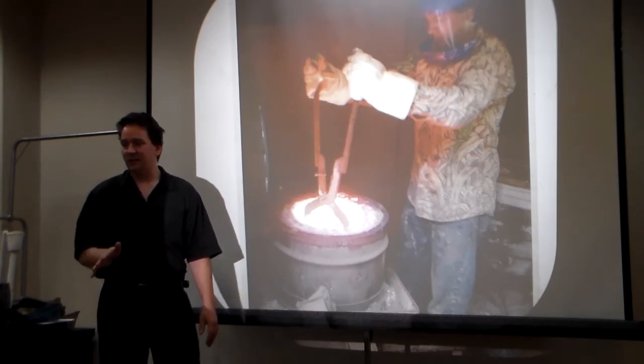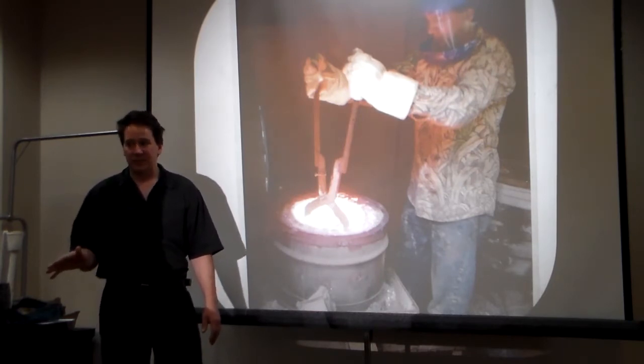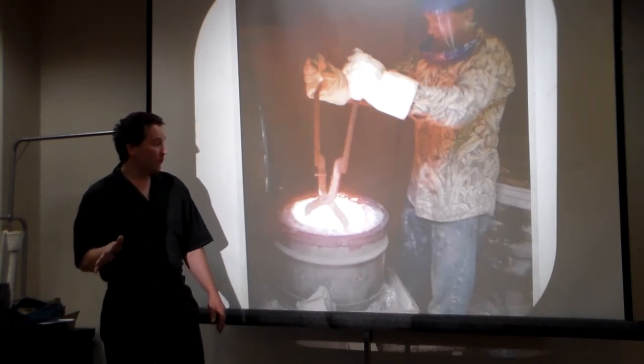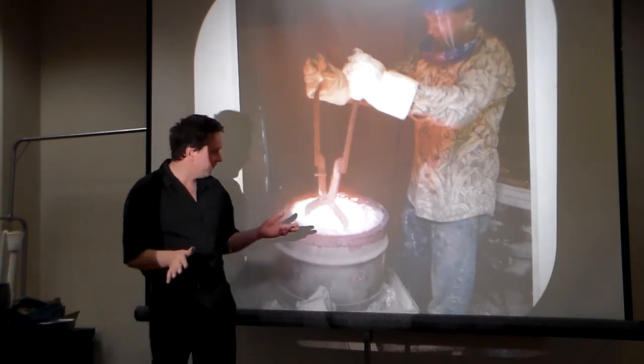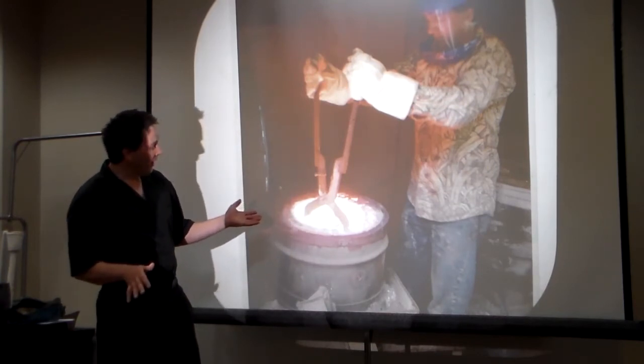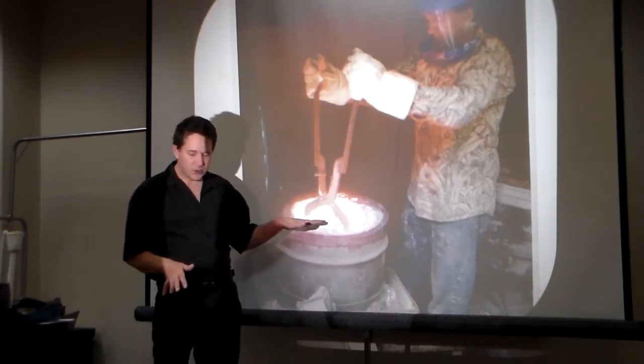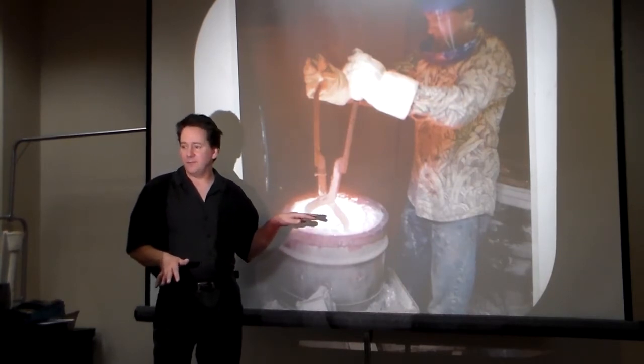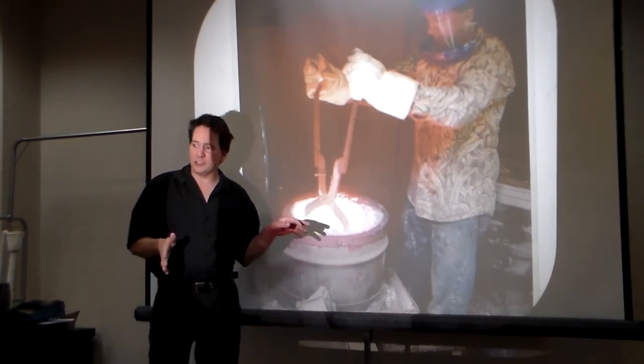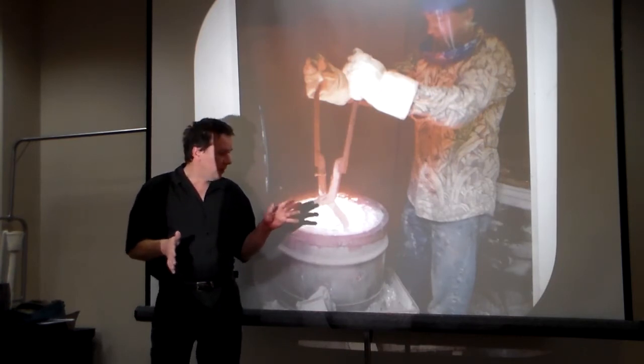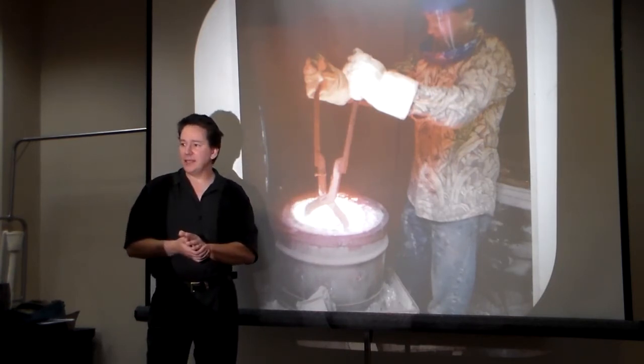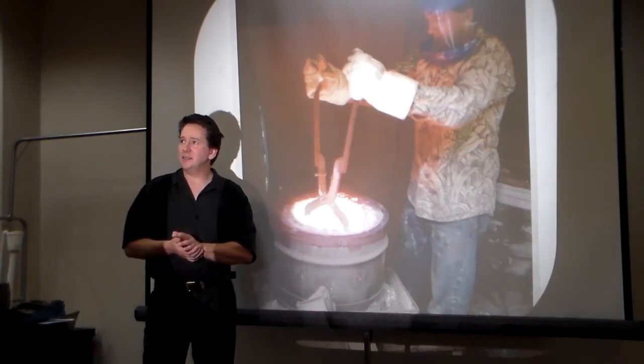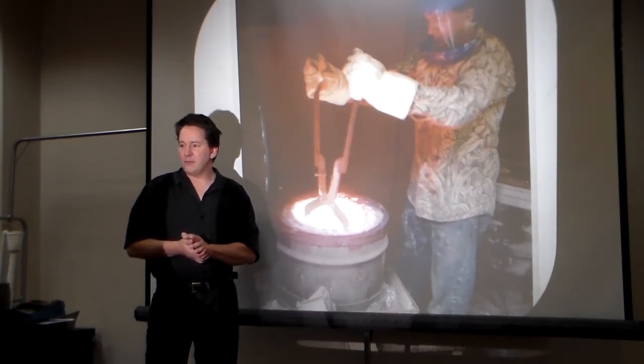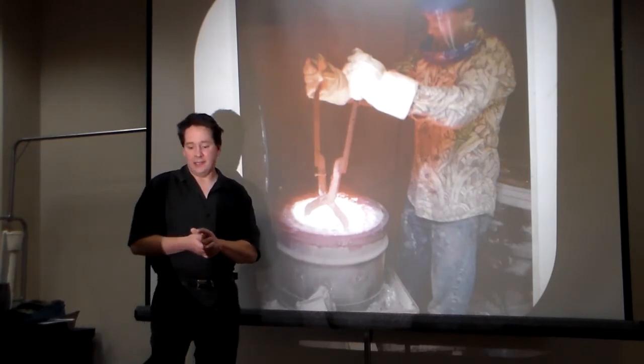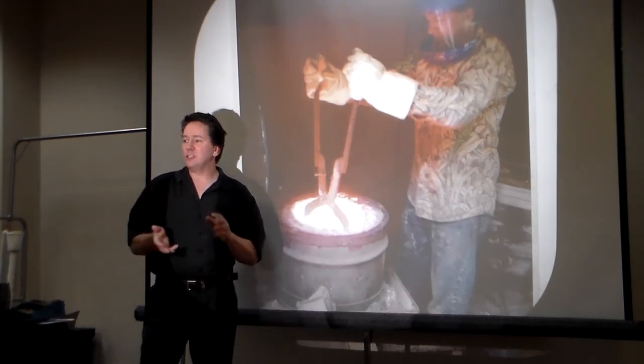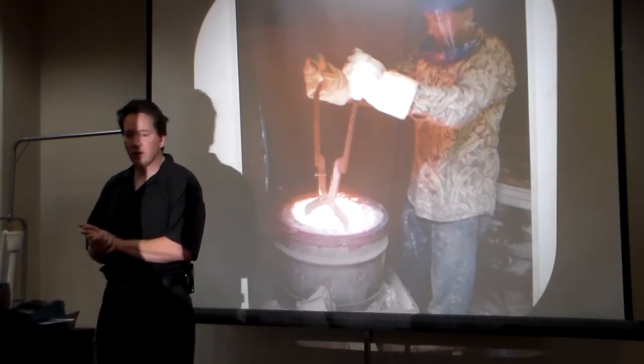Technically, if you wanted to cast steel or stainless steel, the ceramic will deal with that, but we're gentler because we don't need it. Bronze is a much more friendly material. This is a furnace I got, propane fired, where I've got my crucible in there heated up to 2050 Fahrenheit, which is the average temperature for these mid-quality bronzes. For very thick castings like table legs and so forth, you don't need but 1950 Fahrenheit. But if you're casting things with a lot of fine detail, including jewelry grade detail, probably 2150 Fahrenheit is as hot as you want to go.